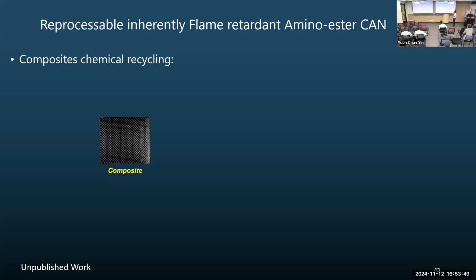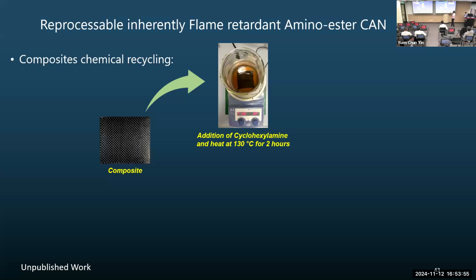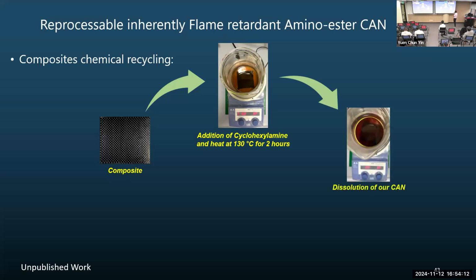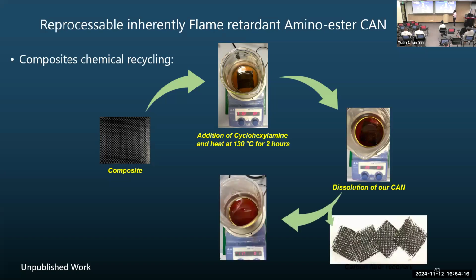What we did was we can do full recycling of this material. So you make a composite material. How do you recover the fibers? Unlike alcohols, you do aminolysis here. So you add in an amine, and what the amine does is it opens up the bond, I would say, and you can recover the fibers. You dissolve the polymer away and you recover the fiber.